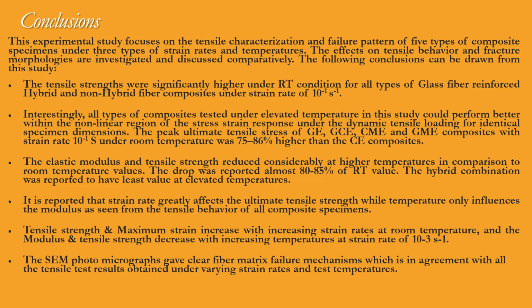Conclusions. This experimental study focuses on the tensile characterization and failure pattern of 5 types of composite specimens under 3 types of strain rates and temperatures. The effects on tensile behavior and fracture morphologies are investigated and discussed comparatively. The following conclusions can be drawn from this study. The tensile strengths were significantly higher under room temperature conditions for all types of glass fiber reinforced hybrid and non-hybrid fiber composites under strain rate of 10^-1 per second.